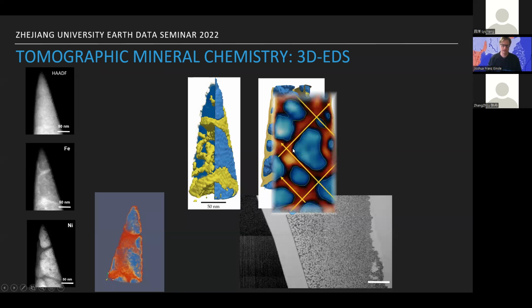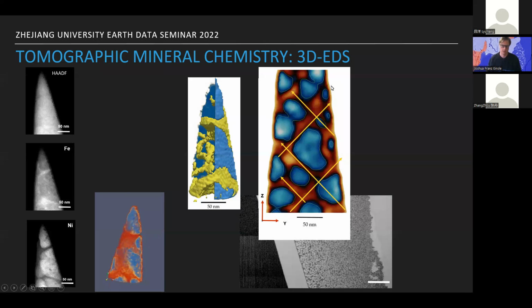And if we look in detail at an orthoslice through the medium cloudy zone, we can see that the grains of tetrataenite are starting to assemble into cuboidal type arrangements, very reminiscent of nickel superalloys. And this gave us a lot of hints about what kind of behaviors we should expect. However, when we first tried quantifying the 3D model that we had rebuilt here, the data was coming out wildly inconsistent.